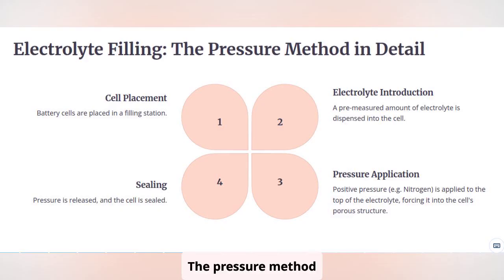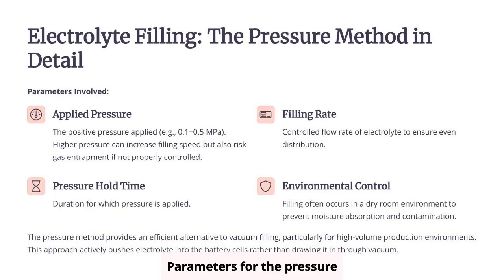The pressure method utilizes positive pressure, often applied using gases like nitrogen, to force the electrolyte into the cell. This method can be efficient, particularly for high-volume production. Electrolyte is introduced under controlled pressure, pushing it into the electrode pores. Parameters for the pressure method include the applied pressure, filling rate, and pressure hold time. While higher pressure can speed up filling, careful control is needed to prevent gas entrapment. Filling is typically performed in a dry room to maintain electrolyte purity.